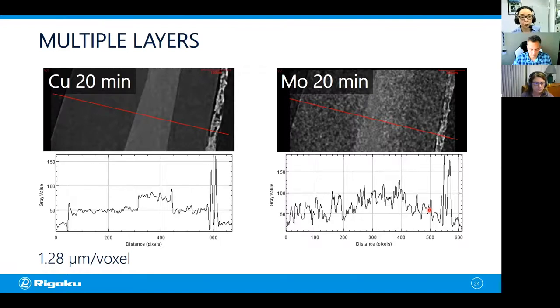Now, to give you an idea of what kind of density difference we're talking about here, UV resin's density is 1.12 grams per cubic centimeter. And this layer is 0.92 grams per cubic centimeter polymer. Parafilm, they do not disclose the recipe for parafilm, so I can only speculate, but it should be anywhere from 0.9 to 0.95 in density. So those two layers might have exactly the same density, then it makes sense that they look the same. But you can clearly tell the difference between 0.92 and 1.12 with the copper radiation.